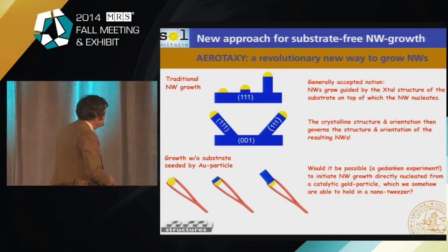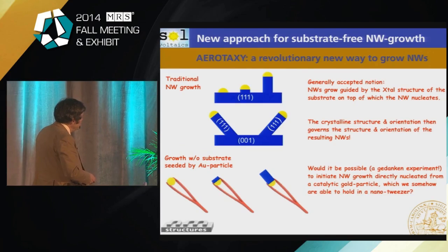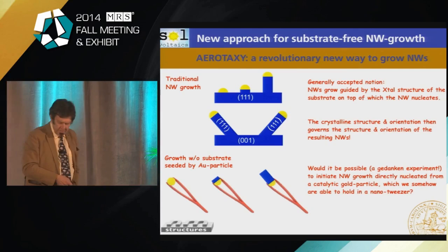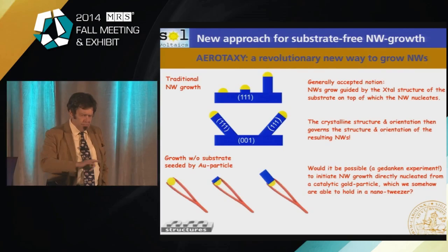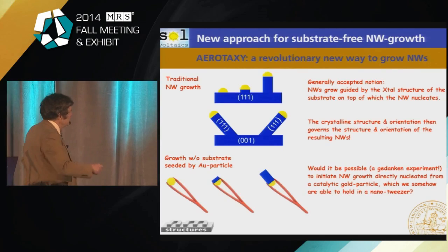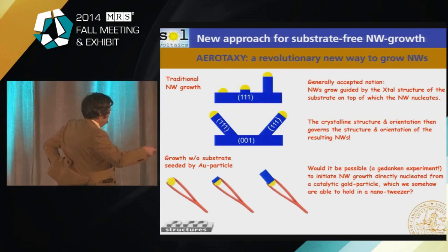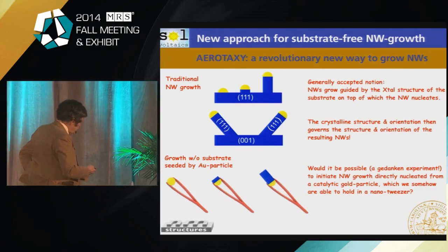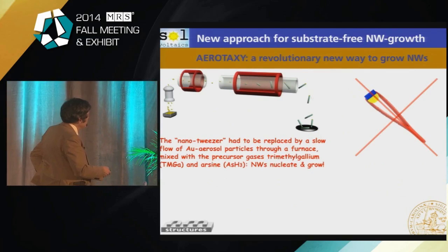And I bet that this system is going to find a low energy, an ideal nucleation spot, and I bet it's going to grow in the 1-1-1 direction. This will not be limited by the stagnant layers typically you have on the wafers, but this is going to be a particle and a wire that can interact with all the molecules surrounding it. So the nano-tweezer, people said, no, you're not going to get that from us.